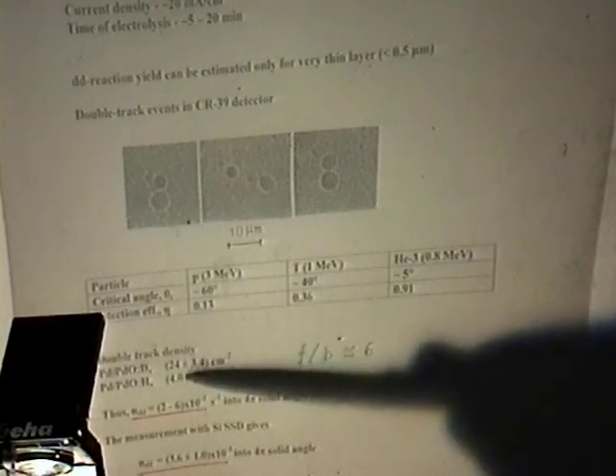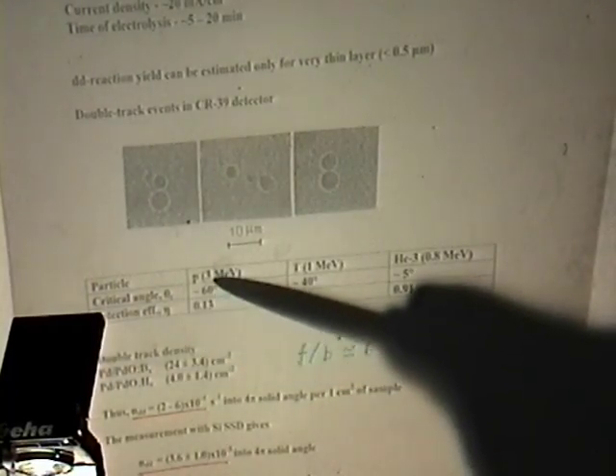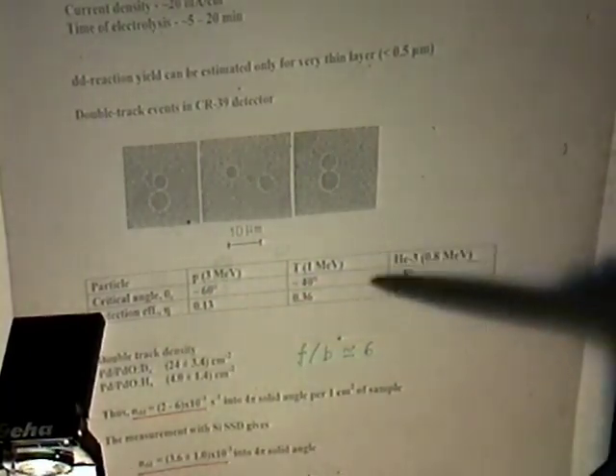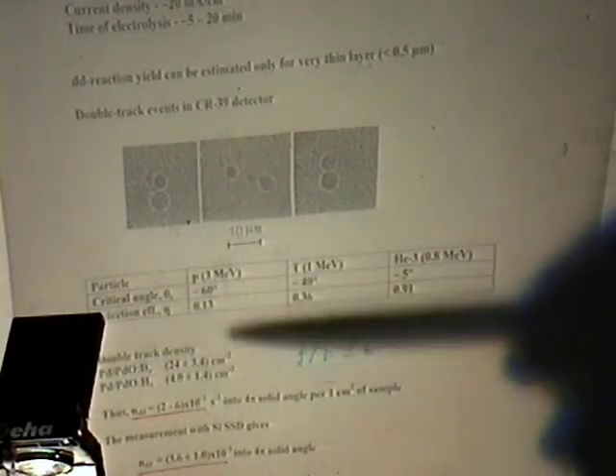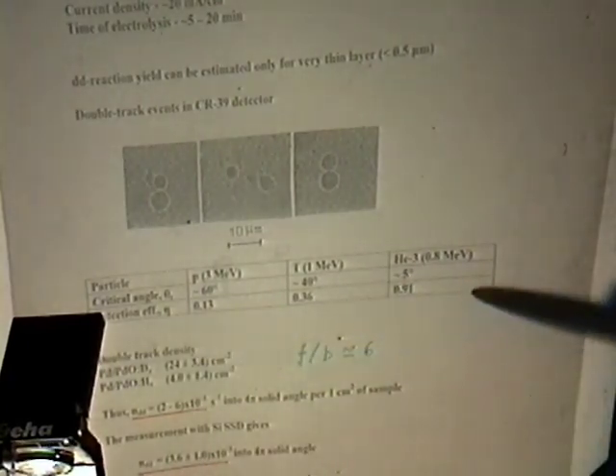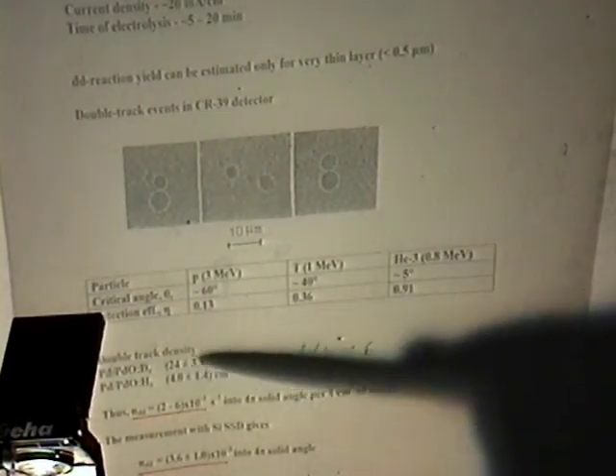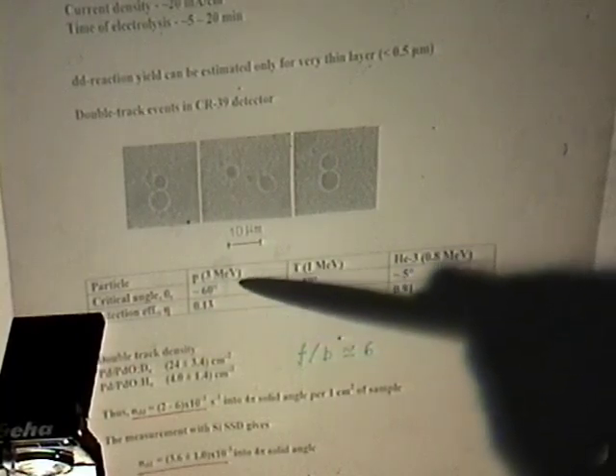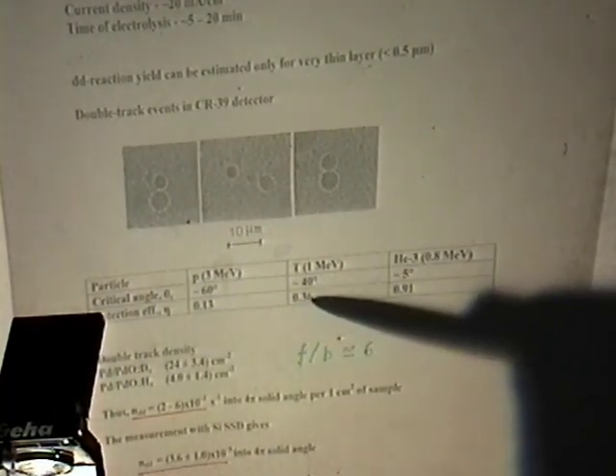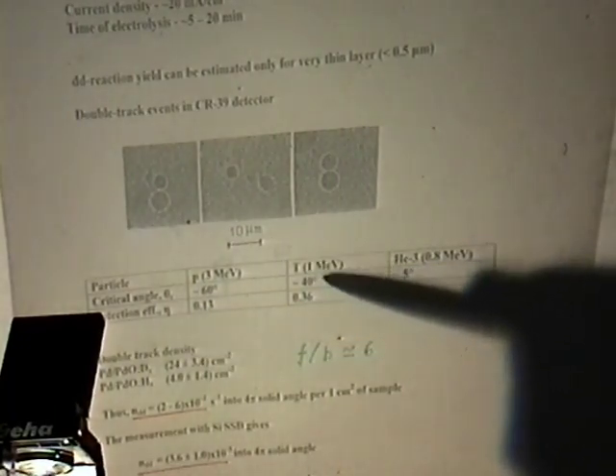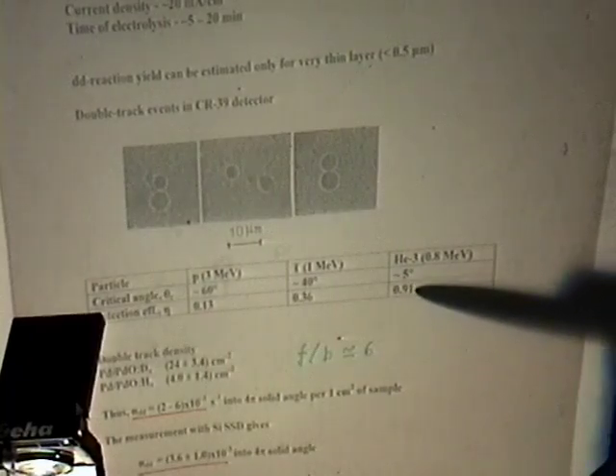As we know the critical angle of registration of proton, tritium and helium-3 with corresponding energies, we can estimate the detection efficiency of these 3 types of particle as 0.13 for proton, for 3 MeV proton, 0.36 for 1 MeV tritium, 0.91 for helium-3 with energy 0.8 MeV.